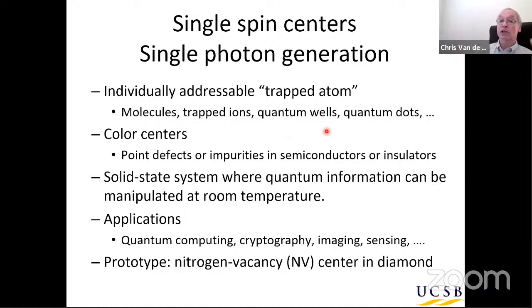So that's the idea of using quantum wells or quantum dots, or using point defects, very often referred to as color centers, which was the original term used for point defects in alkali halides. And these are, for instance, vacancies, missing atoms, or impurities in materials that have a band gap, semiconductors or insulators. So this then gives you a solid state system where quantum information can be manipulated, preferably at room temperature. Okay. As already mentioned, the prototype of this is the NV center in diamond.